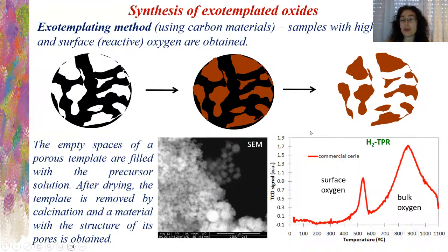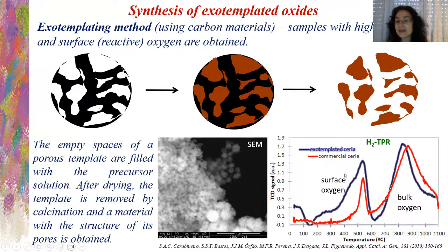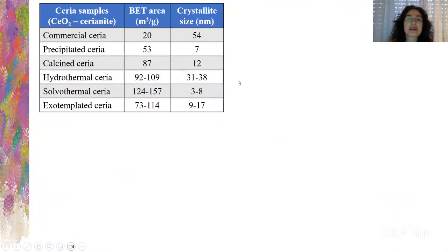So if we compare these results of the commercial ceria with the exotemplated ceria, see, it has a lot more surface oxygen, because this method allows it to have that, and also a higher surface area. So you see here the BET area, if we compare the commercial ceria, it is 20 square meters per gram. This one a bit better. The exotemplated, see, it has higher ones, but if you compare the hydrothermal and solvothermal, they have even higher areas. So that depends on what we want to do.